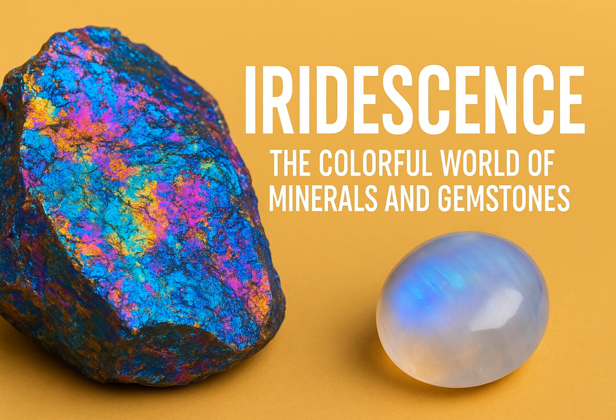And while the pure bismuth metal itself is a rather unassuming silver-white with maybe a hint of pink, its astonishing iridescent colors are not from the metal itself. Wait, really? Not from the bismuth? Not directly from the bulk metal, no. That's a crucial distinction. The vibrant iridescence is caused by microscopically thin surface films of bismuth oxide. Oxide films again, like on bornite. Exactly like on bornite, but formed during the cooling process in the lab.